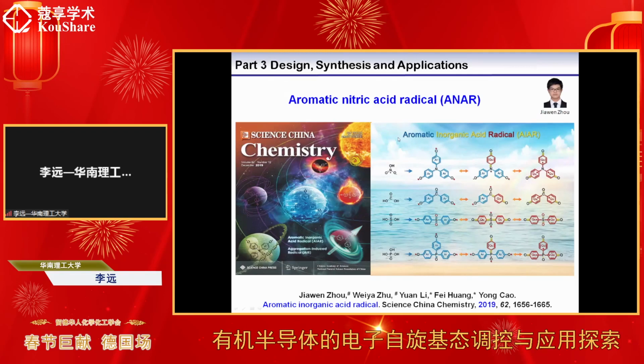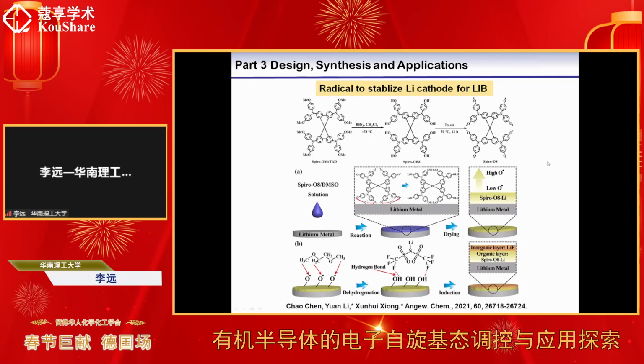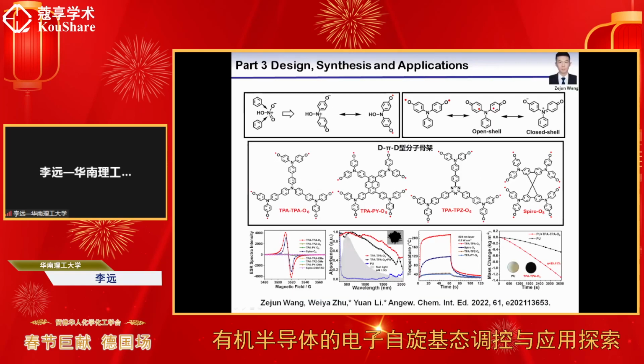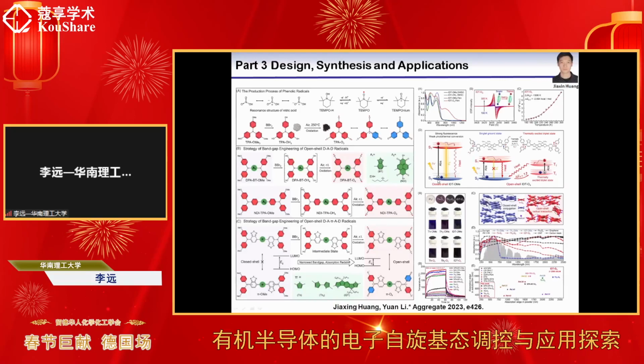For example, we prepared this kind of spiro radical, and it showed very good stability in air, and also very good stability in the CV test. We used this radical to stabilize the lithium anode for lithium batteries. And for photothermal conversion, we prepared this kind of radicals, and we found that they showed very high photothermal conversion performance. And also in the DA-pi-AD type of radicals, we further enhanced the photothermal conversion properties.